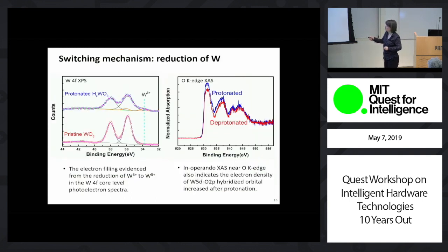And also from the core level tungsten 4f states, we can see the formation of tungsten 5+ states, which is also consistent with electron donation to tungsten. And from oxygen K-edge measurements that we performed at Brookhaven National Lab, the NSLS, we can see the intensity increase in an energy range, which represents the tungsten 5d oxygen 2p hybridized orbitals, whose intensity also increases after protonation.